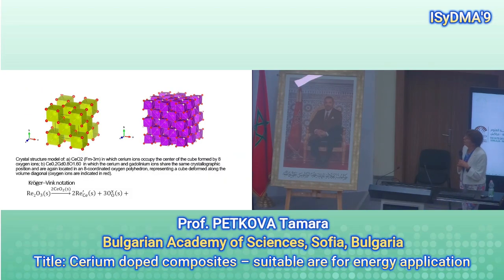Okay. So, what are our conclusions after all this investigation? The unit cell of the cerium oxide, which we see on the left side, is deformed, but not destroyed, after introducing gadolinium. This is a cubic form still, but deformed along the volume diagonal due to the presence of gadolinium, which facilitates and induces vacancies and defects that make these changes in the structure.